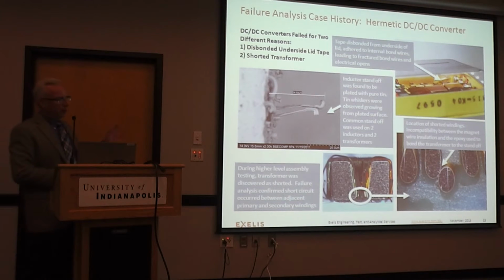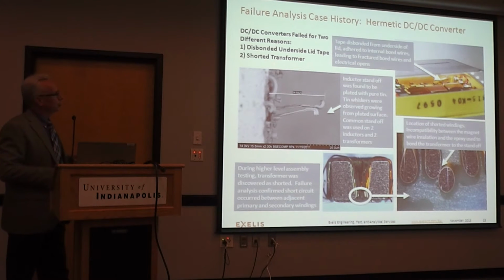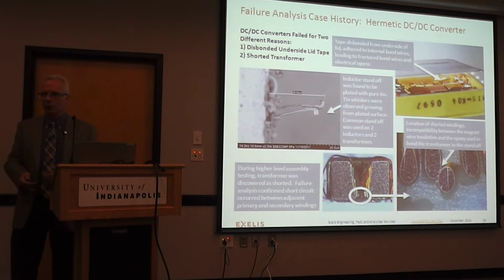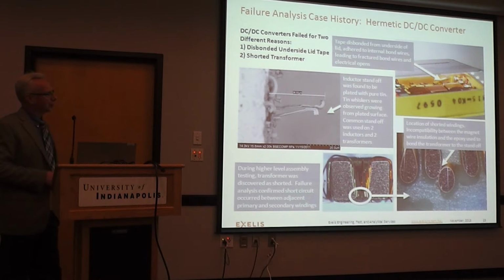All right, so this was a hermetic. This is the case history that involves a hermetic DC to DC converter package. So think of a metal box with leads sticking out of it to make contact electrically with the outside world. And there is an inert atmosphere sealed into this case, this can, if you will. And in this can, this DC to DC converter failed. And actually there were two, this was kind of a rare bird, and it's very rare to have two causes of failure in a single failure. But in this case, this is almost like a system within a can, if you will. There's a lot of components within this hybrid. And we had two things going on.